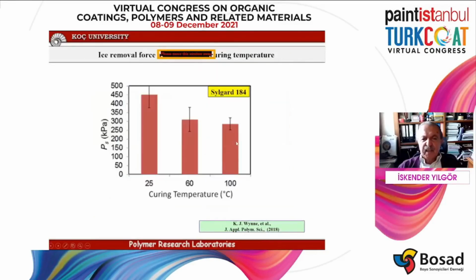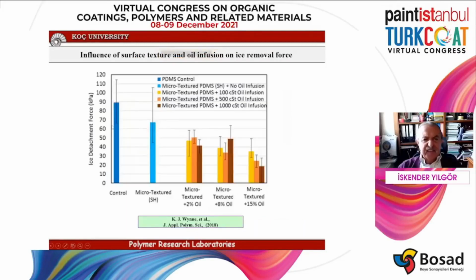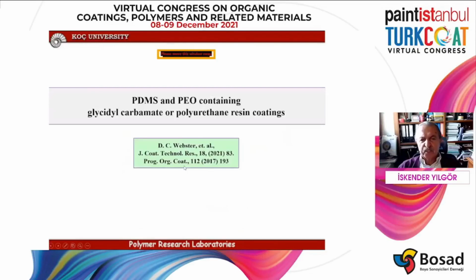Then he showed that if you cure this resin at different temperatures, room temperature versus high temperatures, the results change. At higher temperatures it's lower, but still very, very high. And then he asked, what happens if we texture the surface and add some oils? As you can see, by adding different types of oils, you can come down to almost 20 or so. So this is interesting.